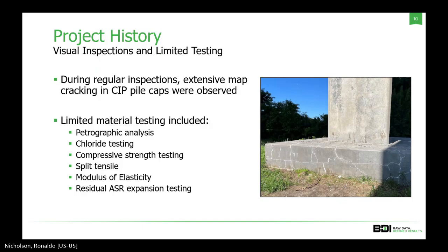So like Nick mentioned, during regular inspections, extensive map cracking of these pile caps, as you can see in the photo on the right, was observed. From that, some limited material testing from WC and others in previous years included petrographic analysis, chloride testing, compressive, split tensile, modulus of elasticity, and then some residual ASR expansion testing.